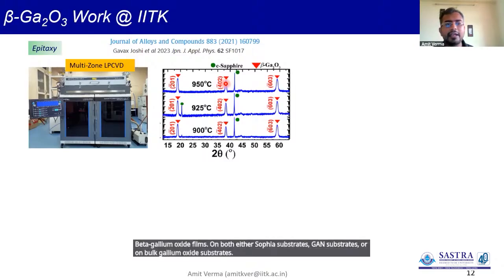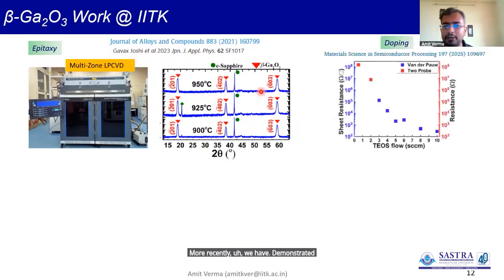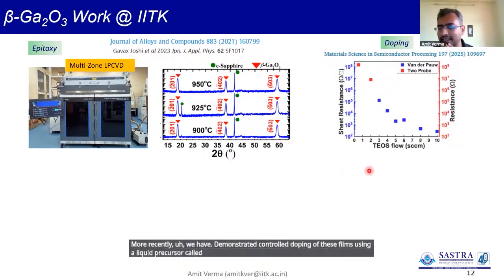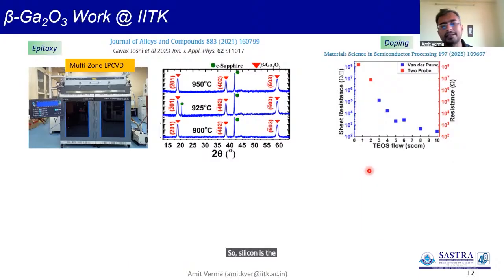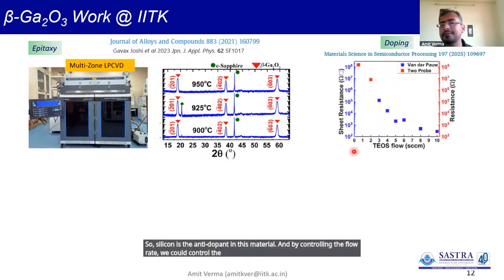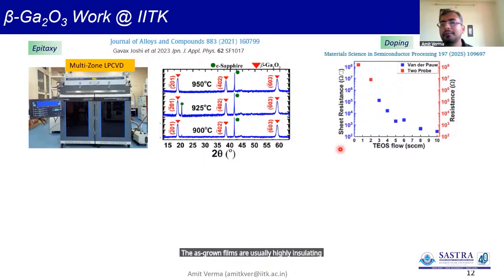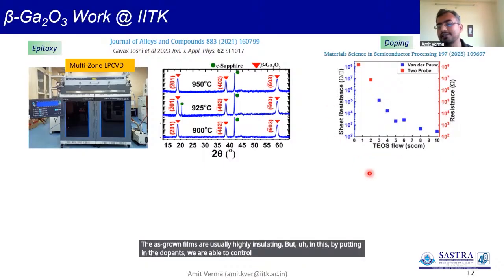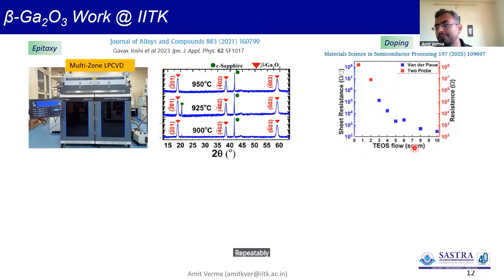More recently, we have demonstrated controlled doping of these films using a liquid precursor called tetraethyl orthosilicate. So silicon is the N-type dopant in this material. And by controlling the flow rate, we could control the sheet resistance by almost 6 orders of magnitude. The as-grown films are usually highly insulating, but by putting in the dopants, we are able to control the resistance repeatably. When we do Hall measurements, this converts to controlling carrier densities from 10^17 to about mid 10^19 per cubic centimeter or so.